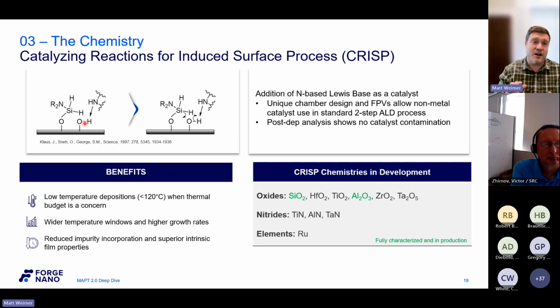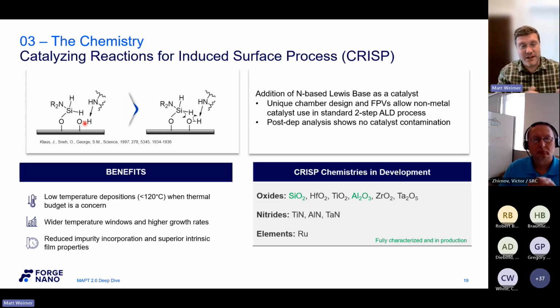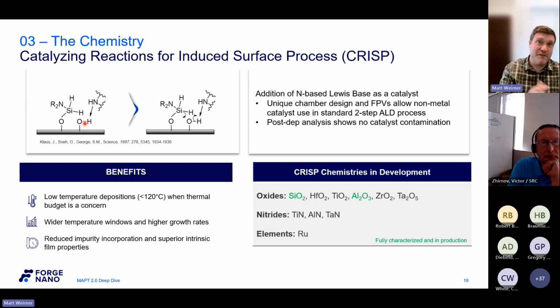Now, just a little bit of backstory here on the life and times of silica. There's quite a large kinetic barrier to forming that bond. So fortunately, the whole field of catalysis, which has been around for a few hundred years, already had a solution. It was just a matter of applying that solution to surface chemistry, which has also been done. So this really takes advantage of decades or even centuries of fundamental catalysis research to apply a very simple and elegant solution. Now, the key here is you have a non-metal catalyst. I want to stress that.